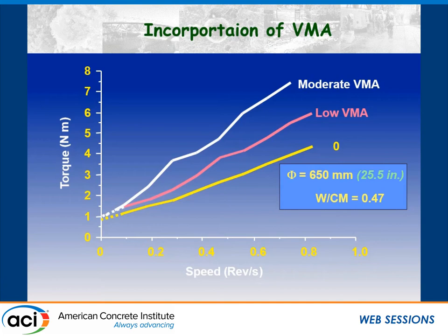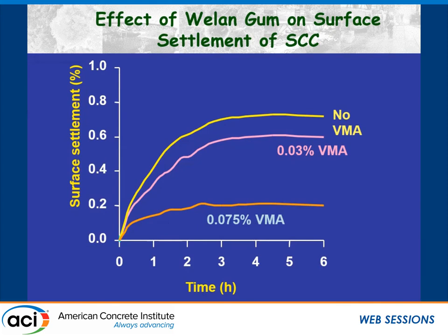You can also reduce surface settlement, i.e. increase plastic viscosity of an SCC, by using viscosity modifying admixtures. As you add VMA, the slope increases, and you also have to add more superplasticizer to maintain the yield stress, of course. These all have the same water to cement ratio. If you look at the surface settlements, SCC without VMA, you get about 0.6%, small dosage, 0.5%, much higher dosage, 0.2%.